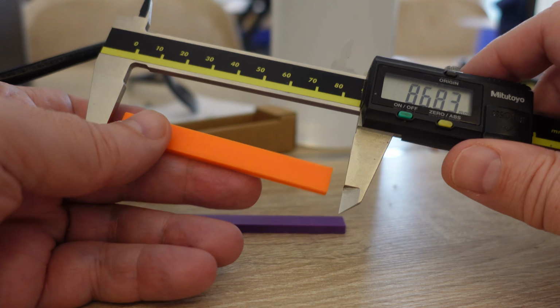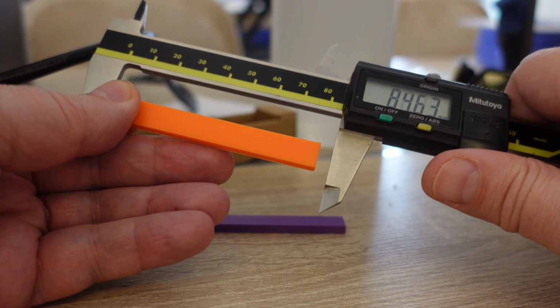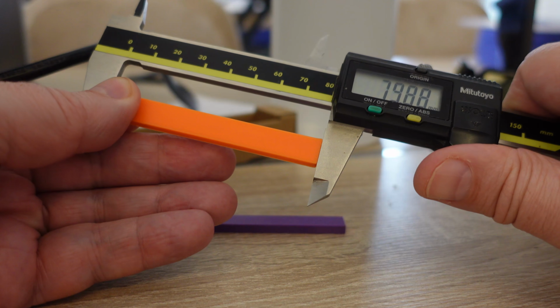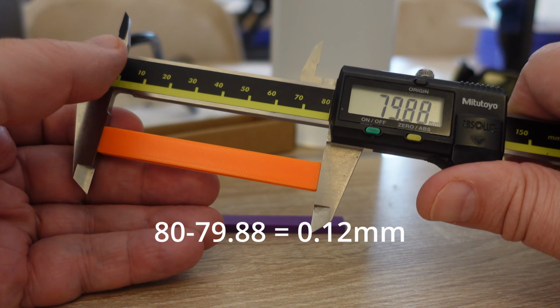I think I found the reason for that weaker bed adhesion. This is PLA, and usually PLA has extremely minimal shrinking, but this is 0.12 millimeters, which is quite big for the PLA.